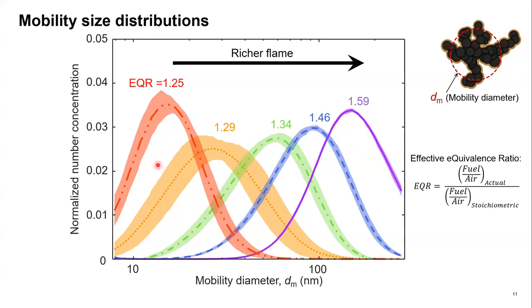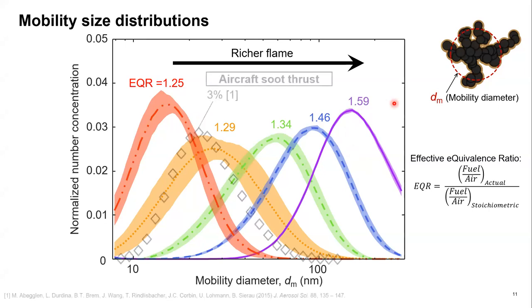As we would expect, richer flames lead to larger particles, and this is because in a richer flame, more particles are nucleated from the beginning. More particles means more collisions and more coagulation, resulting in these larger, more agglomerated structures.